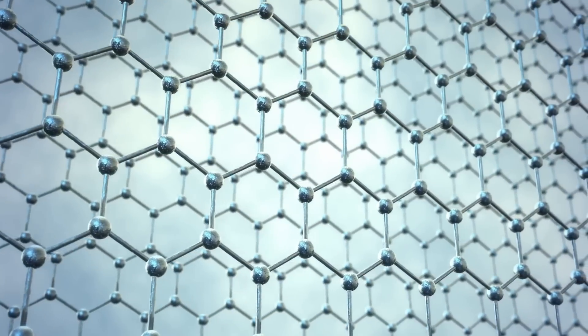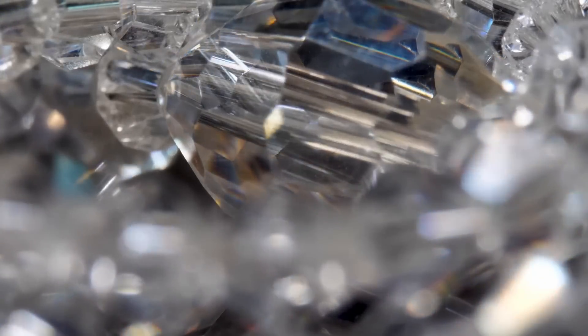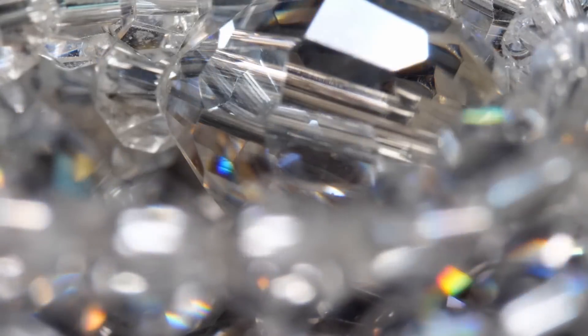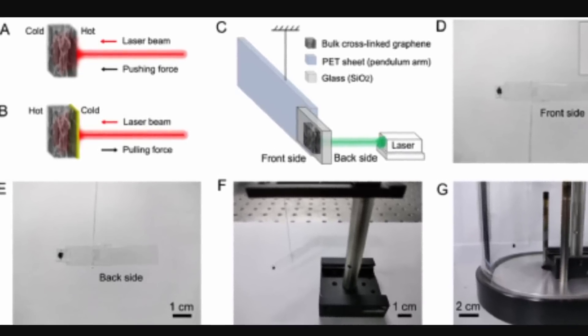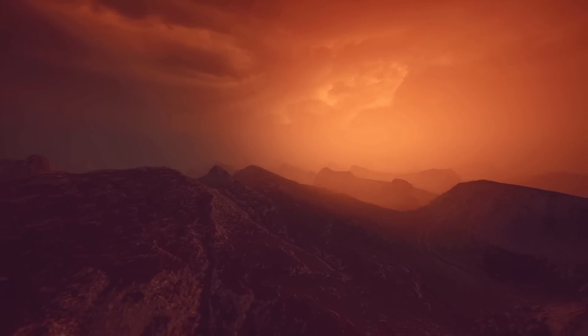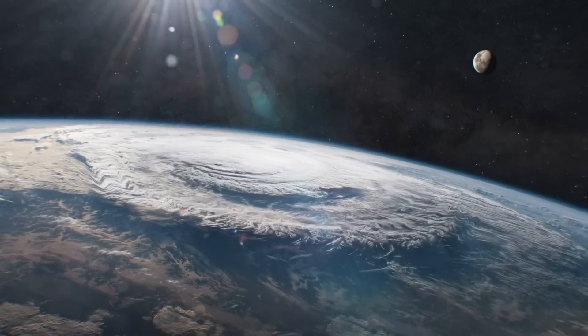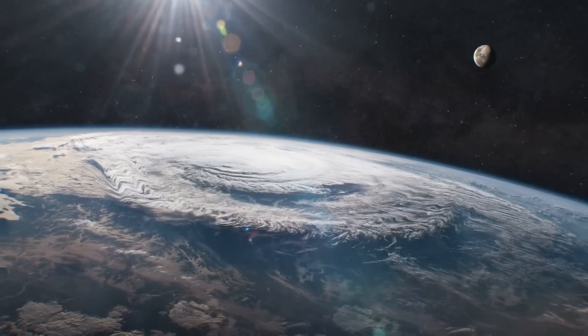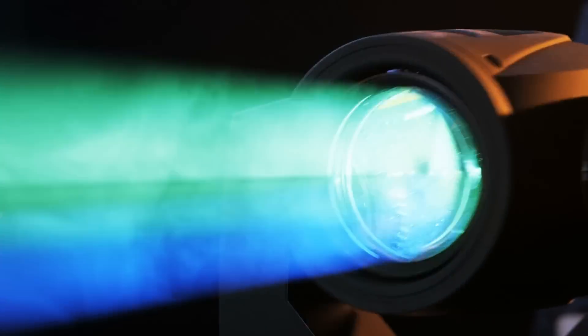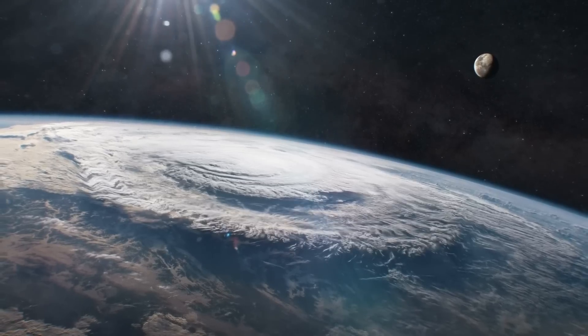They made a material containing two different layers: one made out of graphene and the other made out of silicon oxide — or in other words, glass. Glass in this case lets quite a lot of laser light through, which makes one side warm up much faster, and in this case it's the side facing away from the laser. They then also lowered the atmospheric pressure to 5 Pascal — not really vacuum, but definitely much lower than pressure on Earth, and actually even lower than pressure on Mars. In these low air pressure conditions, they were then able to observe the laser pulling on the object and actually physically moving it, as seen in the video. This is achievable if the right material is used and if present in somewhat low atmospheric conditions.